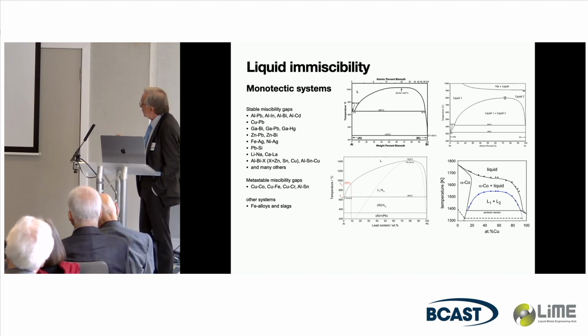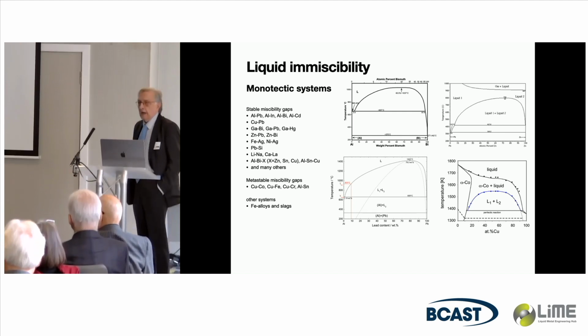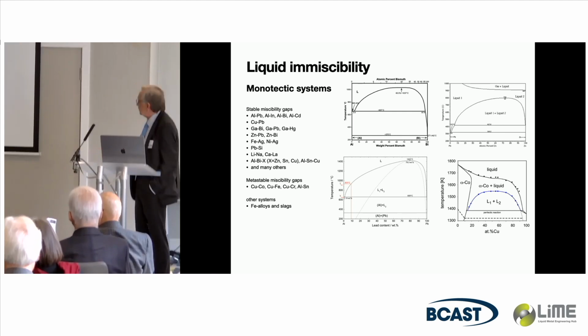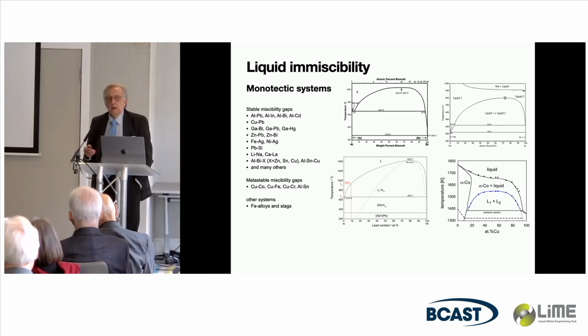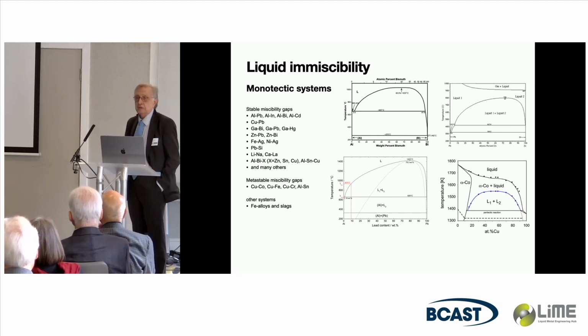But there are also metastable miscibility gaps. For instance, copper-cobalt, copper-iron, there are metastable miscibility gaps. How to reach that? Here you would simply do deep undercooling of these melts. You melt such a material, let's say in an electromagnetic levitation facility, do that in vacuum or in inert gas,